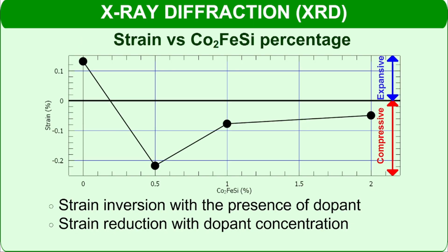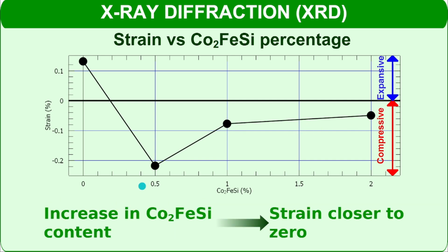Upon completing the X-ray diffraction analysis, we observed shifts in the CeO2 peaks. Using Cohen's method, we plotted a graph of strain percentage versus dopant percentage. The results showed that with the incorporation of the CFS, there was an inversion in the type of strain, where the strain at 0.5% CFS had a higher strain in modulus. As the CFS concentration increased, we observed a reduction in the overall strain of the film. As the dopant concentration increased, we obtained a CeO2 film with strain approaching zero.